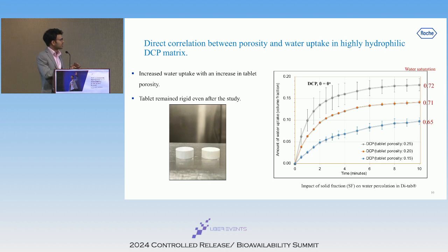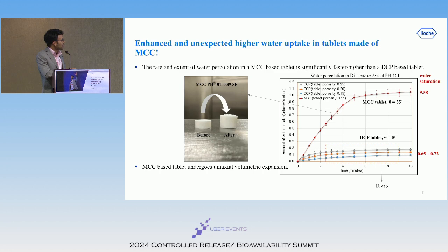So this suggests that for the DCP tablet, the water uptake only runs through the pores. And if the tablet lacks pores, if the tablet is compressed at very high compaction forces, then we hinder the DCP's ability to uptake water, and that may result in poor disintegration and dissolution performance.